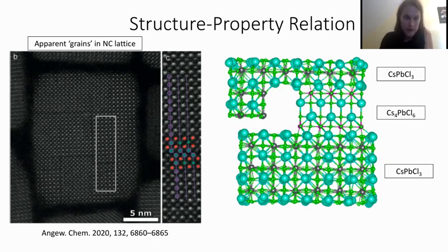And they had at their disposal high resolution TEM. And what they found is that for the very highly doped samples, there were these essentially like micrograins within the nanocrystal. And they identified them as Ruddlesden-Popper defects. So in this B figure, if you look to the right, they have a color code of purple lines where they don't match up at the intersection. And so where green meets green, that's where they think that this Ruddlesden-Popper phase occurs.